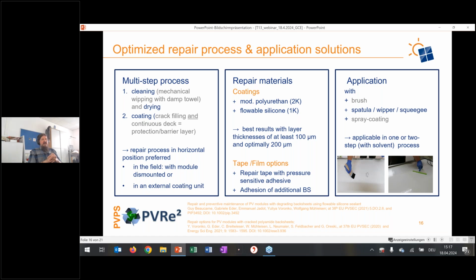That could be a 1- or 2-step application for crack filling and continuous deck. Obviously, it's easier when you dismantle the module and do the process in a horizontal position, but we also did in-field repair without module dismounting. For the repair materials, we found a modified polyurethane 2-component coating and flowable 1-component silicone coatings to show the best results, where we applied thicknesses between 100 and 200 microns. We also tested different tapes that we adhered. And how did we do the application? With spray coating, with brush, or, very efficient, with a squeegee, where you can cover larger areas quite efficiently, and with some exercise, also very consistently.